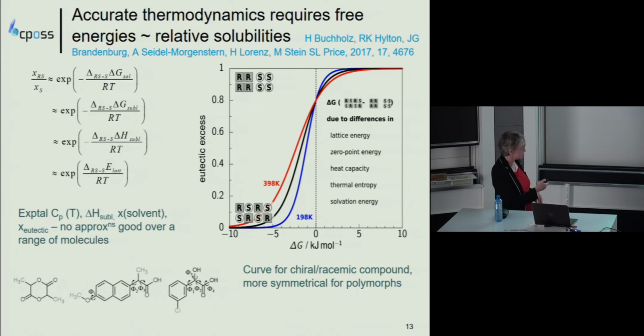And you can see it's rather a tight curve. If the lattice energy difference is big enough, you know that you can't do it, but it is very tight there. And, you know, think of the sort of approximations you might make. The ratio of the relative solubilities of the 2 crystals depends on the exponential of the energy differences of the solvation, of the free energy of solution of the 2 crystals. But it's the same molecule. Surely the solutions are the same, or at least non-ideal to the same extent. So it's just to do with the free energy difference between subliming the molecules. Surely all the entropy effects are going to be much the same, so it's just the heat of sublimation difference between the 2 molecules, and surely your 0-point energies and your heat capacity differences are going to be the same, so it's just the lattice energy difference.